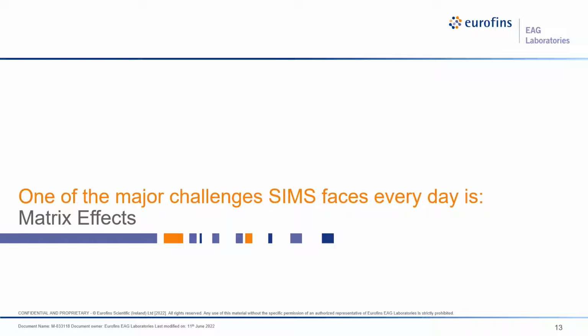One of the biggest challenges associated with the application of SIMS to the analysis of AlGaAs pixels is the variations in aluminum content, which impacts sensitivity of aluminum, the SIMS matrix effect. This means that quantification of aluminum content is not straightforward. Complicating matters further, changes in alloy composition also affect the sensitivities of the dopants and impurities measured in the depth profile, the infamous SIMS matrix effect.